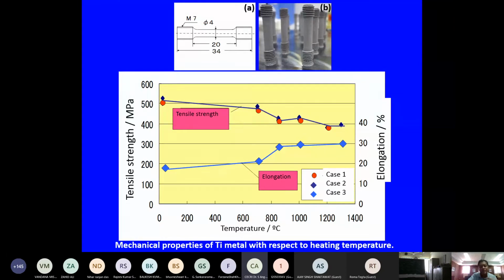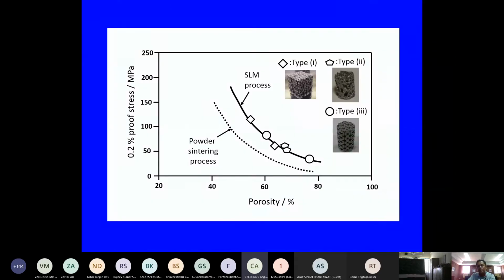But another interesting thing is the modulus or elongation of this material. You can see it goes to 30%. This is very beneficial for bone implant or artificial implant development. And we do a lot of studies on the compressive strength of the material, comparing the strength of the 3D printed sample with the conventional powder sintering process, and we found that this laser melting technique has superior compressive strength compared to the conventional powder sintering process.